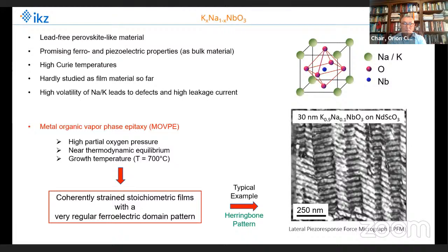Let me first start with the material system potassium sodium niobate. It's a lead-free perovskite-like material with promising ferro- and piezoelectric properties already as bulk material. It exhibits high Curie temperatures, but has been hardly studied as film material so far because of the high volatility of the sodium and potassium, which may lead to defects and high leakage current.